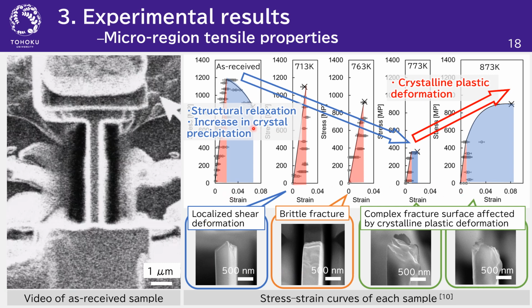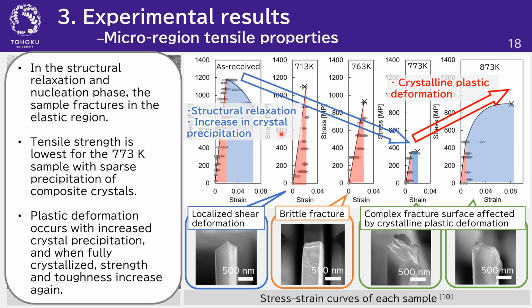To summarize the experimental results so far, the amorphous alloys fractured in the elastic range under conditions of structural relaxation and the beginning of crystallization. The tensile strength was reduced the most in the composite crystals, sparsely precipitated state. Plastic deformation occurred with increasing crystal precipitation. And strength and toughness increased again when the amorphous alloy was fully crystallized.